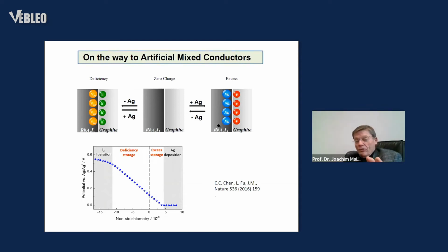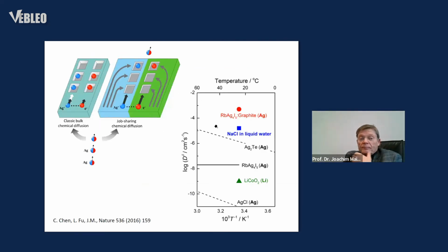But this is a wonderful situation when you go to nanoionics, that you can make artificial electrodes that may even evade the conflict between power and energy density. This can be very fast. So imagine you have your silver ion conductor here and your electron conductor there, and you offer the silver here. Silver ion goes here, electron goes there. You have some support from bulk.